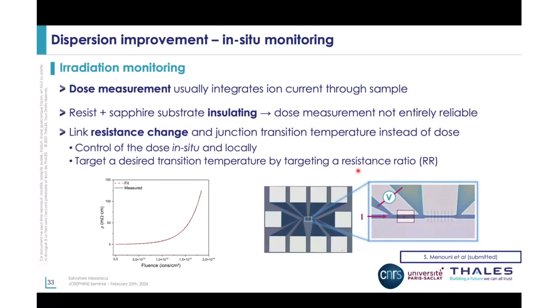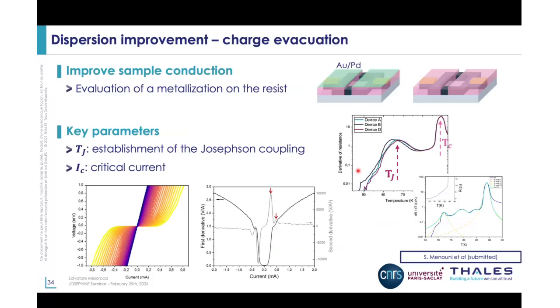So by applying this new in situ technique, and relying on the resistance change instead of just the dose, we were capable of doing a study on how to improve the dispersion in irradiation. And the study was actually making two sets of samples. One set of samples had a metallization layer on top of the resist to improve the charge evacuation during ion irradiation. And one was the classical way without any metallization layer on top. Then we took those devices and we measured two key parameters.